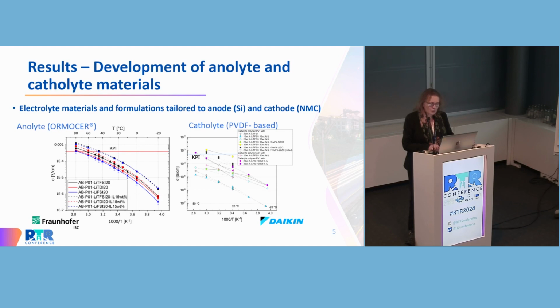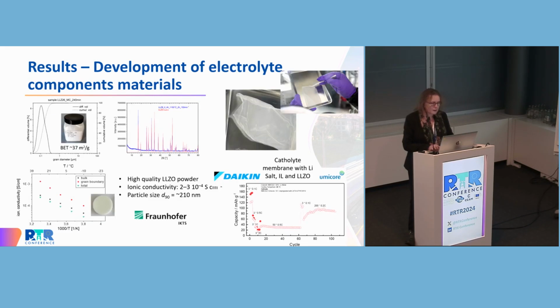For the catholyte, it is the same thing. We have tested different types of lithium salt. Here it is mainly reported LiTFSI and LiFSI. And we have also tested different weight ratios of ionic liquids, and also added some ceramic material in order to be able also to develop a thick layer that is only ionic conductor on the top of electrode materials. This is what has been done here with the LLZO powder.